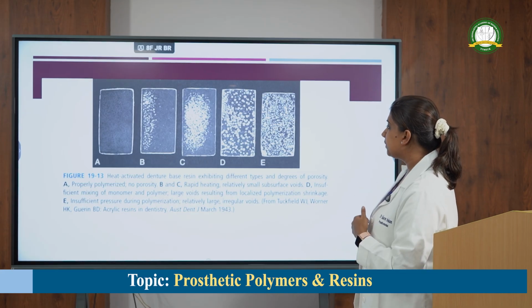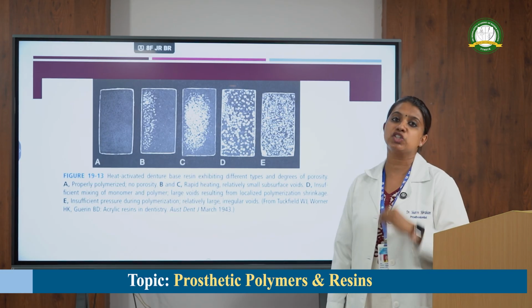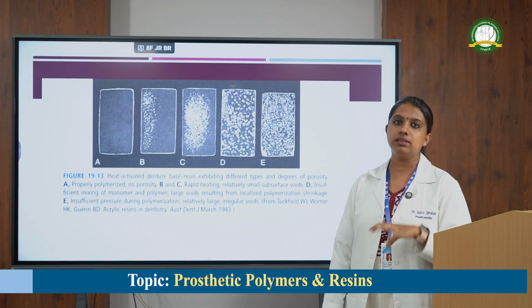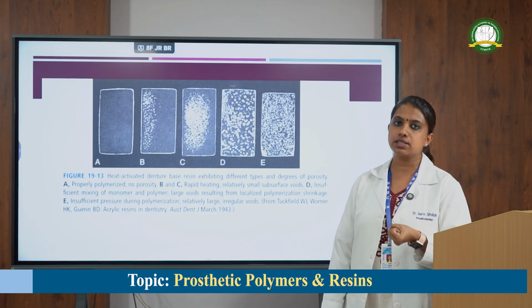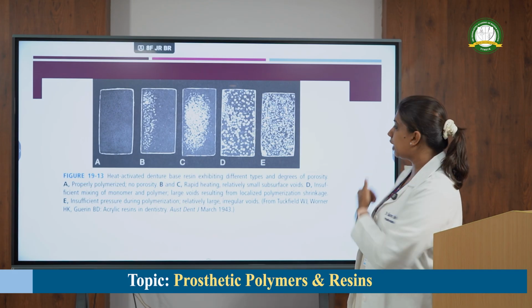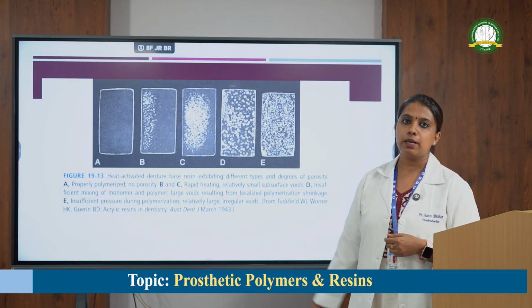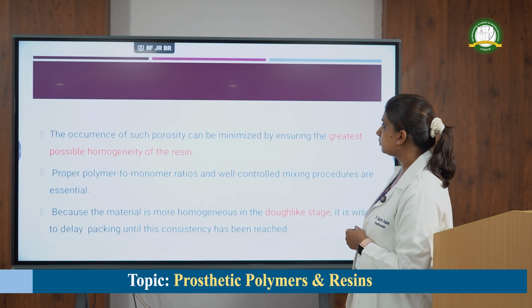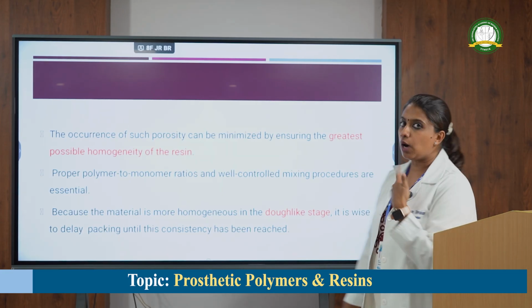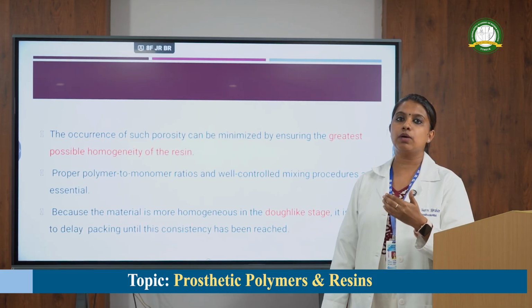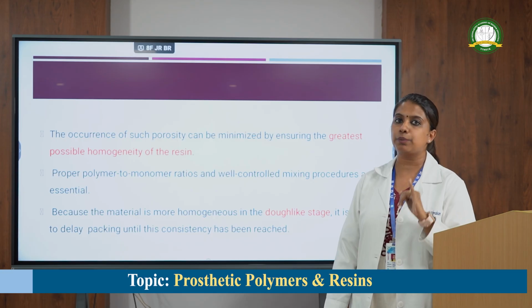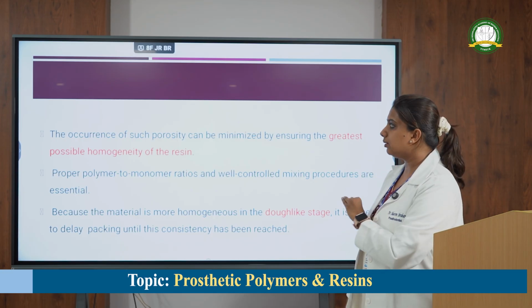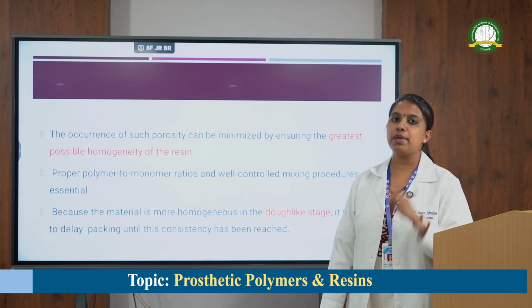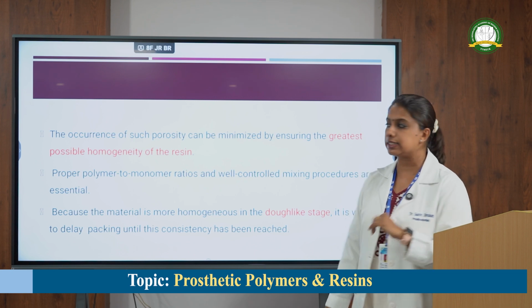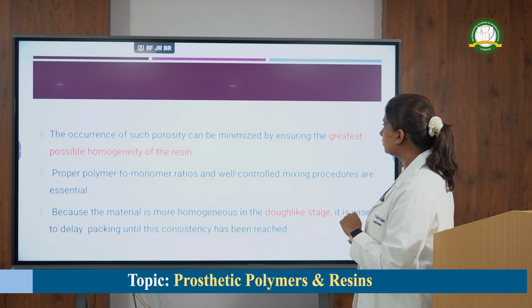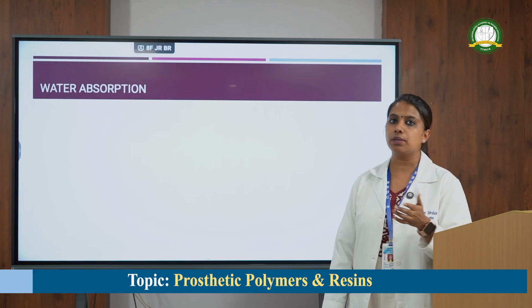Now, in picture E, the porosity was mainly because of insufficient pressure. Once you pack the material, you should maintain some pressure within the flask. If the pressure is not maintained, you can see large irregular porosities like in picture E. Now, how can you avoid this porosity? The porosity can be avoided first mainly by following the proper powder to liquid ratio, and then there should be a homogeneous mix, and make sure you pack it in the dough-like consistency. So all these are the ways to overcome the porosities.